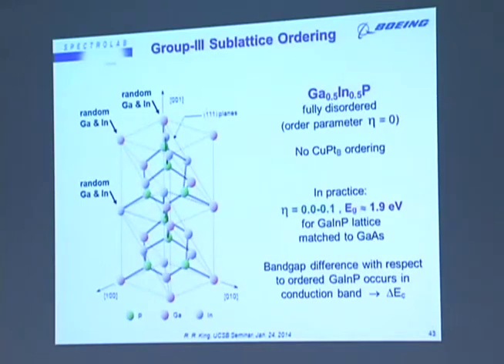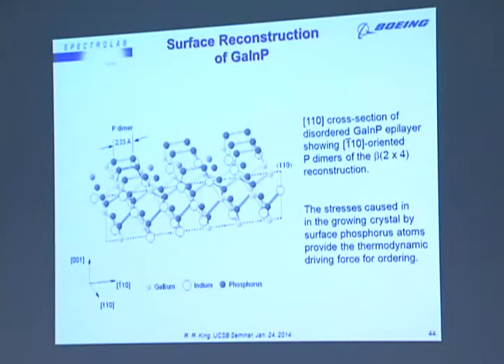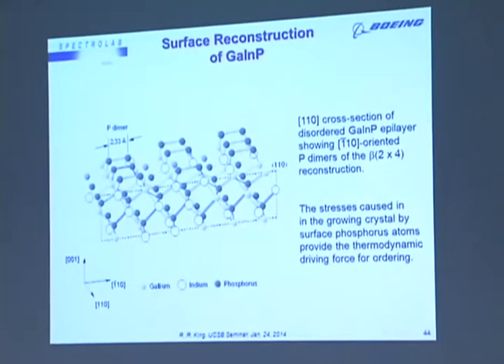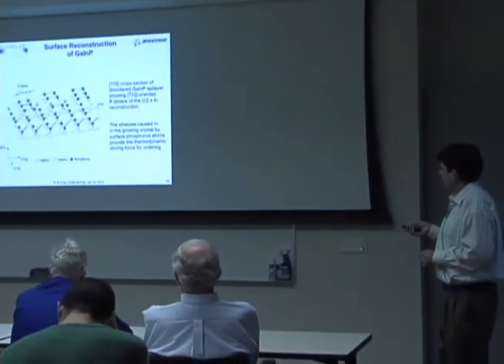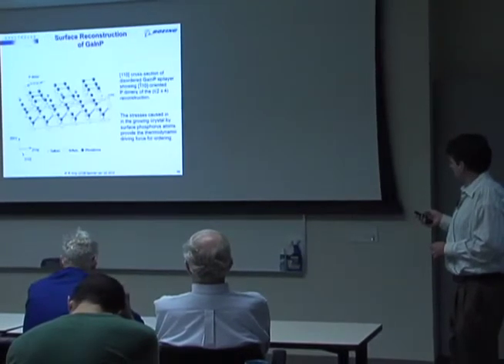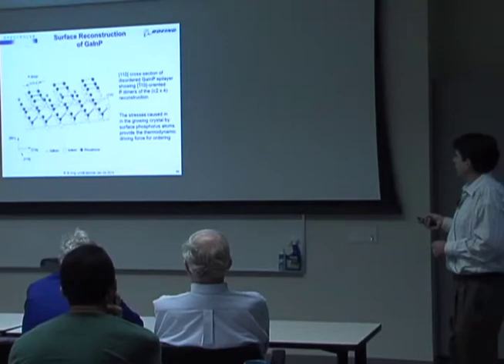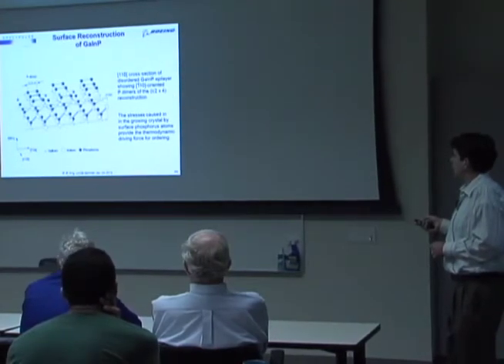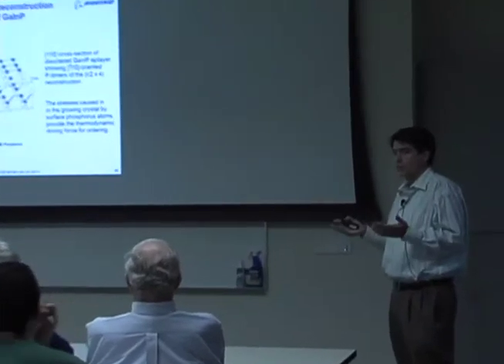So the band gap can go up by 100 millielectron volts as a result of disordering these gallium and indium atoms. That turns out to be very important to achieve a higher band gap top cell in multijunction cells. It's very advantageous to be able to achieve that higher band gap. And the way that arises is stresses in the growing crystal caused by phosphorus dimers that form on the surface provide the thermodynamic driving force for ordering. So mechanisms that disrupt that can result in disordered material and result in a higher band gap, more desirable top cell.